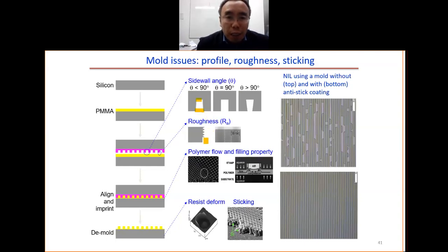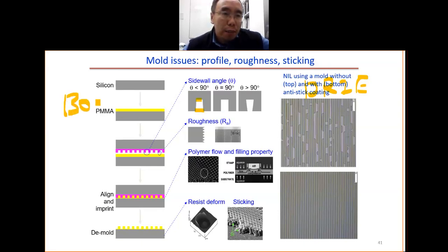For the sidewall roughness, if the sidewall is rough, obviously this is not good for the separation. With this kind of sidewall, you see the ripple, wavy structure, zigzag. This is the typical profile using deep RIE. For deep silicon etching, we use the Bosch process, and we get this kind of wavy sidewall profile. For the mold, we have another issue, which is the polymer flow and filling property. As we see, if we have very big features, the filling may be a problem.